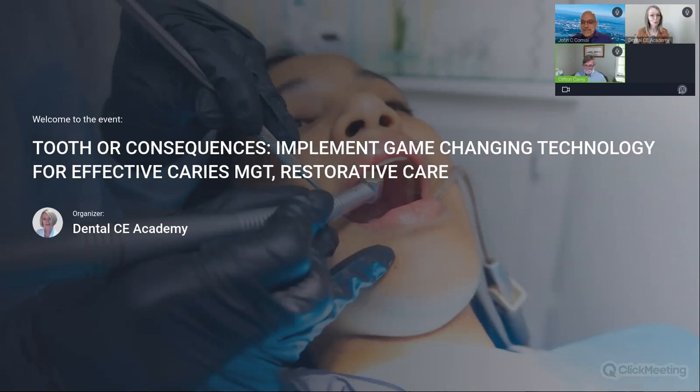There's a question here from Dr. Kuman Wang. PMMA is also a polymer similar to composite resin. Any idea why it did not support microbial growth in a multi-species experiment as much as composite? I believe he answered that, because Cliff answered that, and then Kuman put in, thanks for answering the question, right after it. There it is. Okay. I wanted to make sure that everybody else heard it. Just in case you didn't hear it, the PMMA was not fully polymerized, and so there was toxic methyl methacrylate still able to diffuse from the substrate, and that will kill bacteria, as it turns out. And that goes to the degree of conversion problems as well.